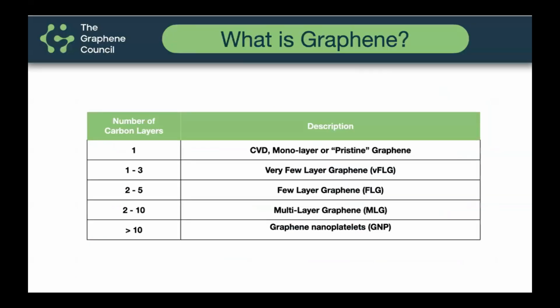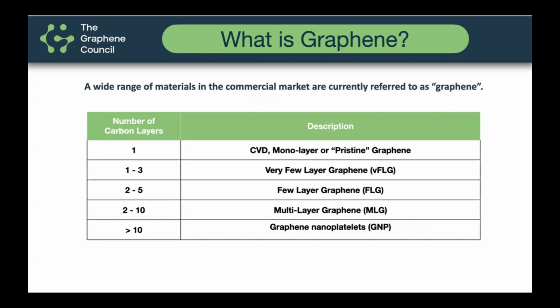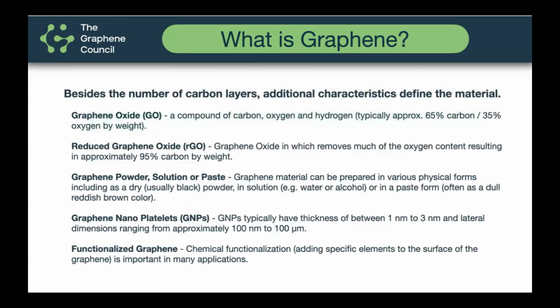But now we need to talk about what really is considered graphene commercially in the real world. From a scientific perspective, one could argue the only thing that is graphene is a single atomic layer of sp2 bonded carbon. But for commercial purposes, and according to ISO standards and evolving other standards, such as with ASTM that we're working on, graphene includes a whole family of materials that includes more than one layer of carbon, up to and including 10 layers, and even graphene nanoplatelets, which would be in excess of 10 layers of the sp2 bonded carbon. Now, besides these definitions, we also have materials like graphene oxide.